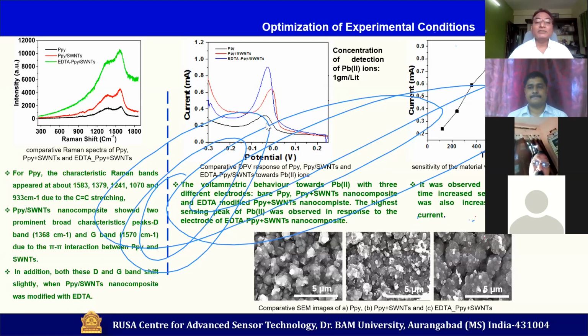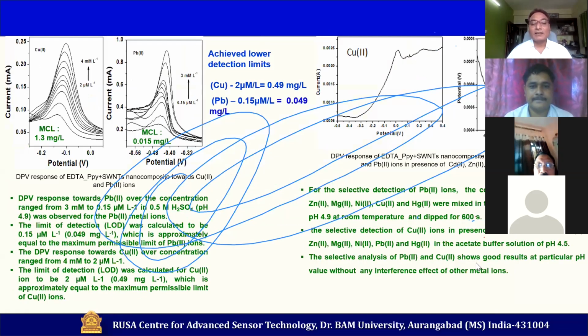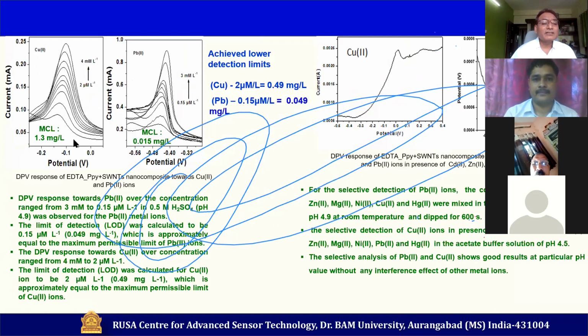You can see here this was with PPY, this was with composite, and you can see this is EDTA modified. It means you can see there is a substantial increase in current. For bare PPY you can see the current level, for composite you can see the current level, and for EDTA modified it is still more enhanced current, and moreover you can see the sharpening in peak as well. And then we went ahead and did a more systematic study. This was a one-shot experiment, and this was a more systematic study.